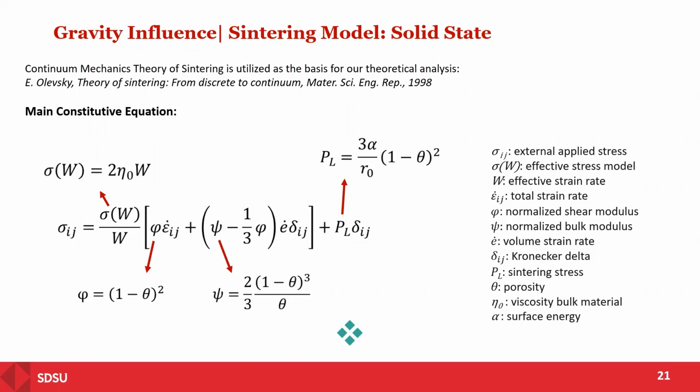This last term here, PL, represents the sintering stress, so that driving force that is a function again of the radius of our particles and the surface energy that helps us to densify our material.